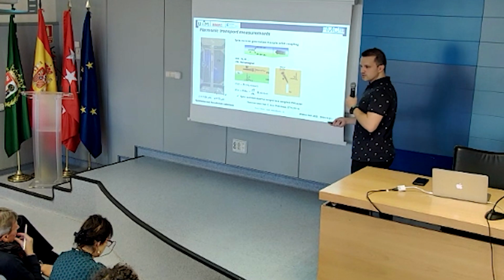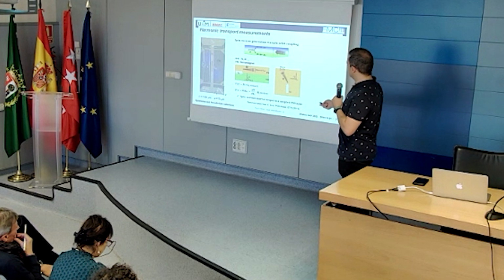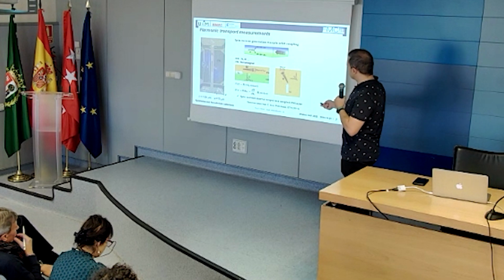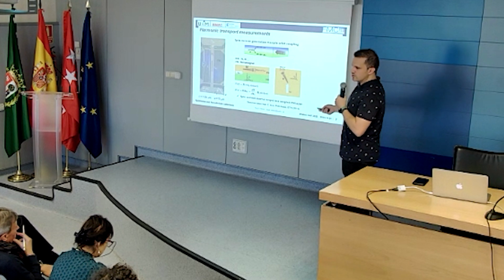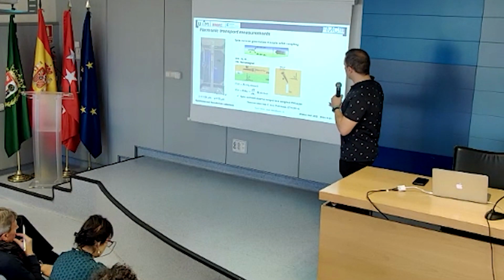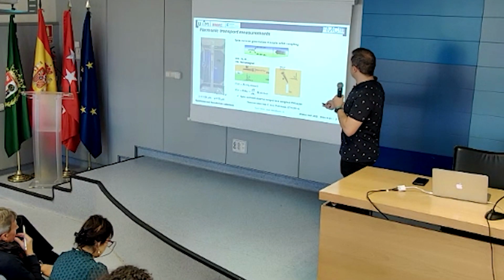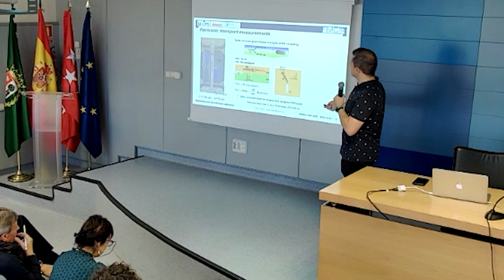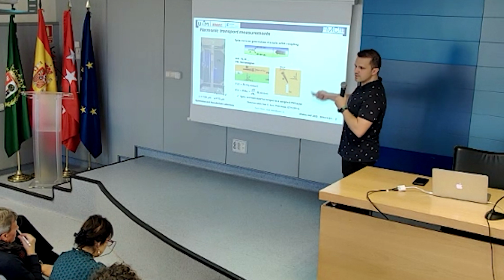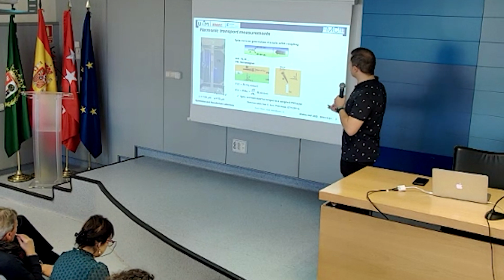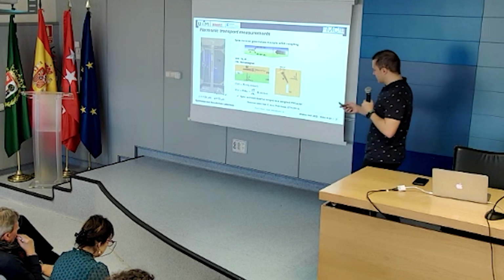There are 2 types of torques. Here is a side view: we have your heavy metal, a platinum layer, and that's our ferromagnet. We typically work with garnet, so that's what I'm going to show you today, a couple of measurements. You run a current, and the spins you generate interact with the magnetization and make it oscillate out of plane, which is called the anti-damping-like torque, and also in plane, which is called the field-like torque.